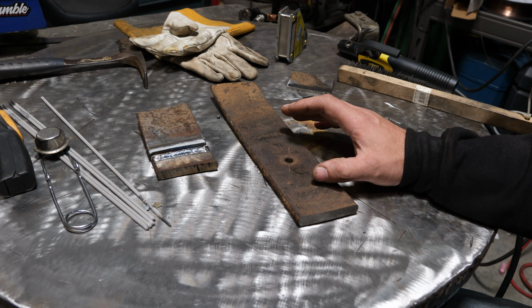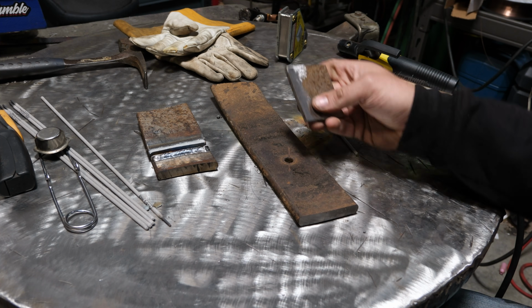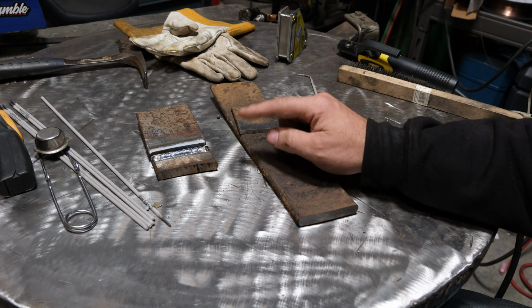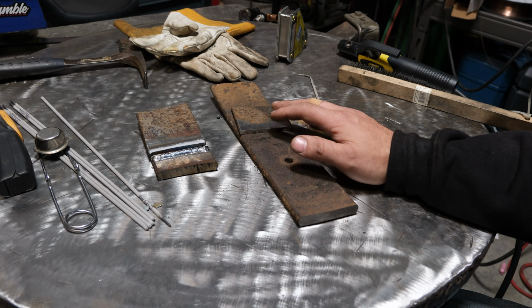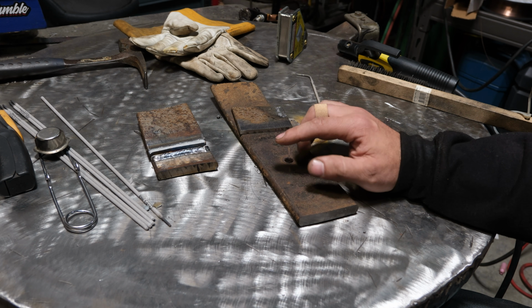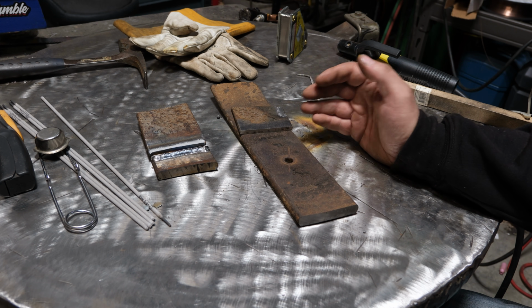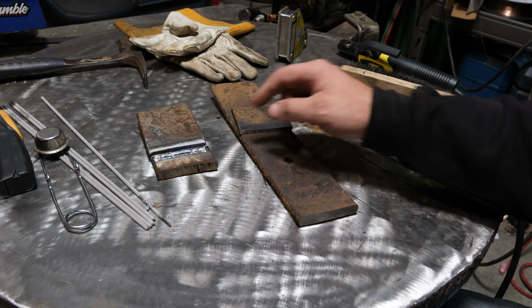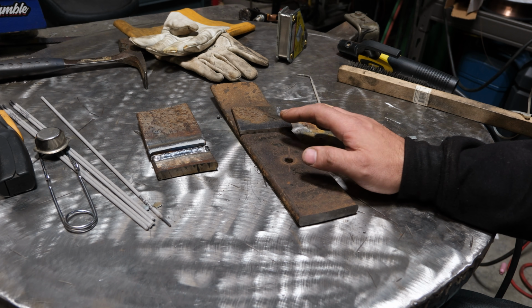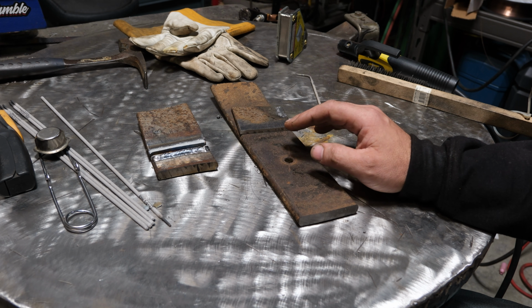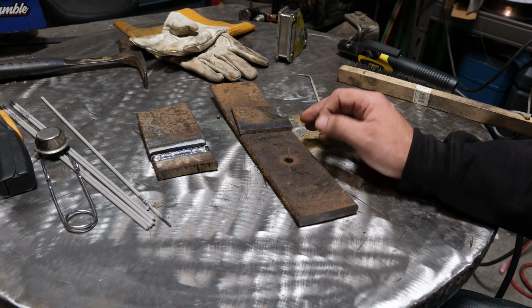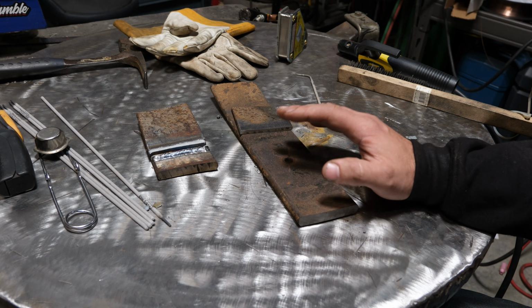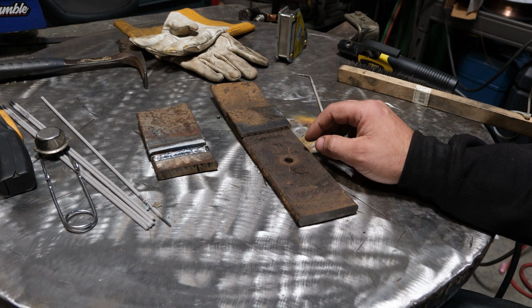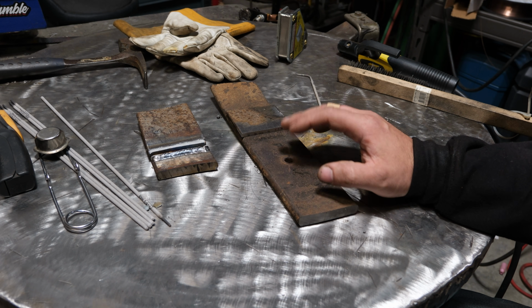And that's why what we're going to do is we're going to take this piece and we're going to weld it onto there. We're going to preheat everything to 300 degrees just the same. I'm going to let it air cool just like I did for this guy, didn't quench it or anything. And then we're going to heat it up to a dull red color and we're going to let it air cool.